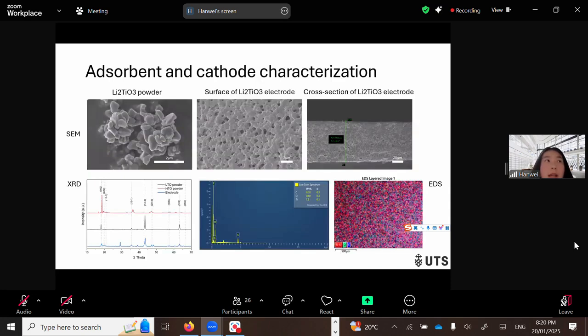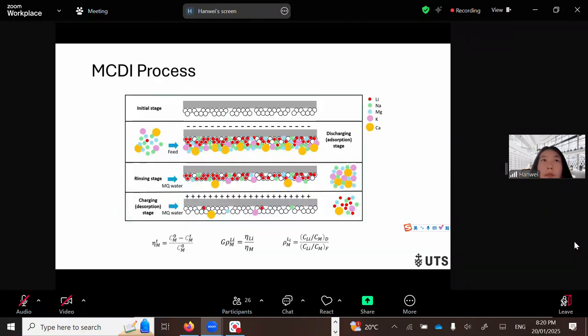Here are the adsorbent and the cathode characterization results. The XRD characterization confirms the successful synthesis of the high crystal LTO, and from the SEM we can see that the LTO electrode is porous. And during the MCDI process, initially we applied -1 voltage on the cathode and allowed the feed solution to pass through, and it takes around 20 minutes. And after that, we have the rinsing stage using MQ water to rinse out the competing ions temporarily on the surface. And finally, we're using MQ water for the desorption.